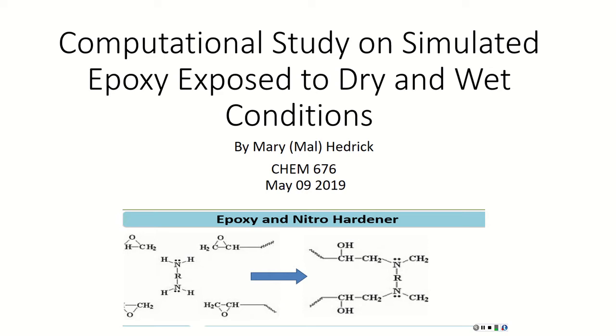So, in a polymeric material, if it's doing what it's supposed to, if you expose it to water, it could plasticize or those kind of things. But my TG was going up, which was showing that my epoxy was becoming more brittle. So it was really hard because we didn't have a chance to do formulations or experience any of that because we have patents that you have to navigate by. But a way to go through this was a computational study.